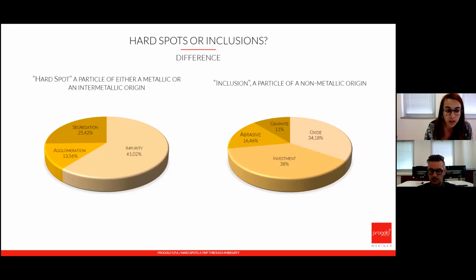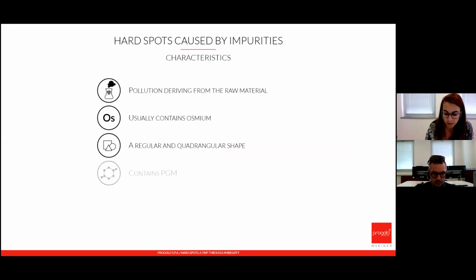So I'm going to start talking a little bit about the first macro category of hard spots, which are impurity hard spots. The most common contamination that we have is when we have impurities from gold, in particular osmium. Osmium is a metal that belongs to the platinoid group, just as iridium, ruthenium, rhodium, palladium, and platinum. And it's very difficult to separate from gold. In fact, there is only one way to separate these elements, which is through electrochemical processes.